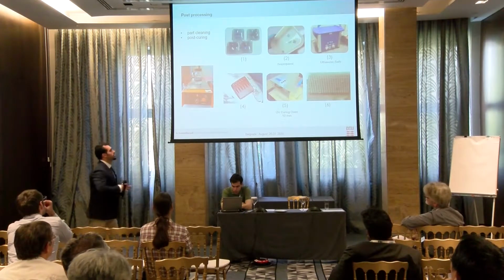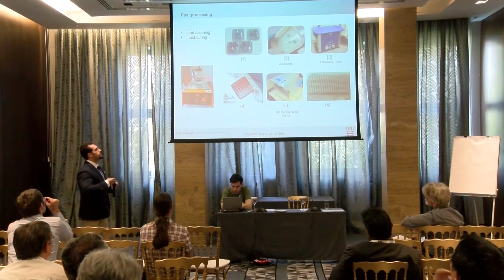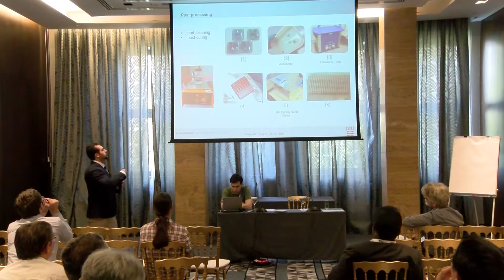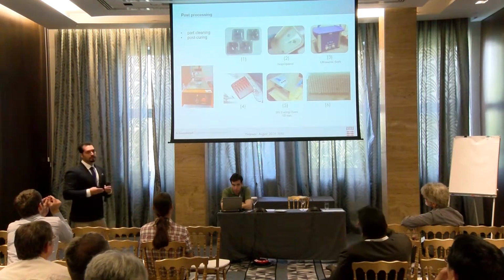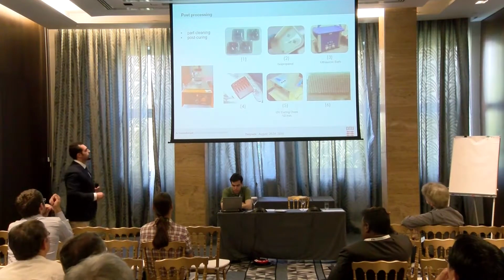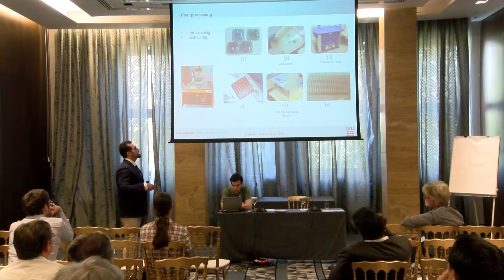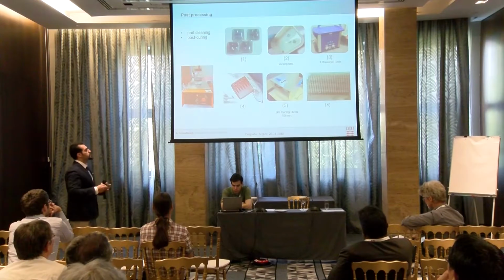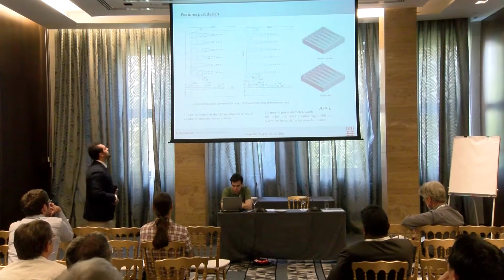Then we gently apply pressurized air, and dry the sample and make sure that there is no resin in between the features. And then finally, the UV curing oven, about 15 minutes to cure the whole part.